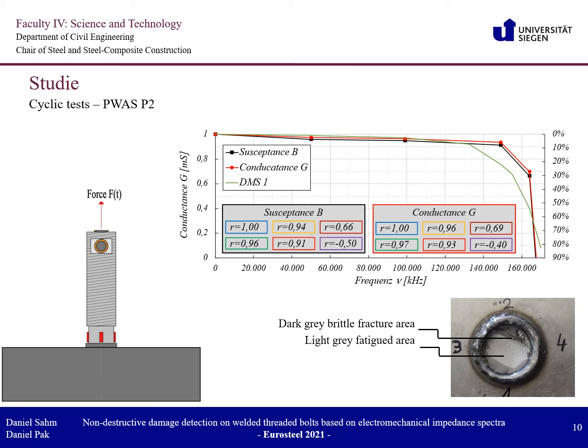Furthermore, the development of the axial strain over the circumference of the bolt shaft was evaluated. The picture shows the qualitative development of the axial strain measured with strain gauge 1, as well as the correlation of the susceptance and conductance spectra after the respective load cycles. Plotting of the related strain has the advantage that the qualitative strains developed can be compared with the data of the EMI measurement. Between 0 load cycles and 132,000 load cycles, the graphs of the three monitoring methods show a very similar trend with a slightly decreased slope.